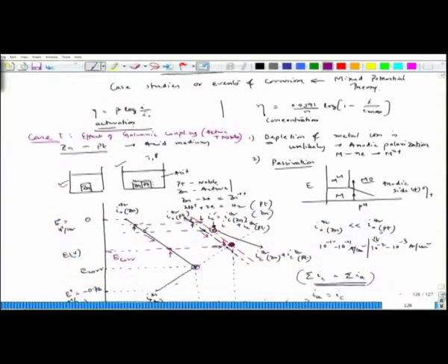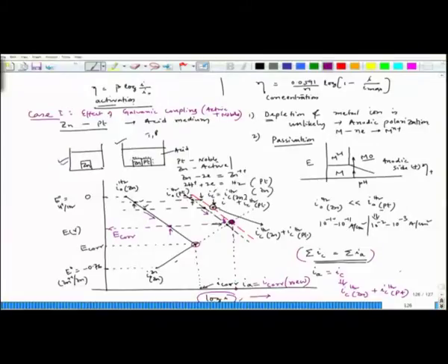But remember, when we have seen this galvanic coupling, we have said that they have the same area exposed to the acid medium. The area is not changing. The active component has some area, let us say 1 centimeter square, then platinum would also have the same area. Now, interestingly, if it is connected to another component, let us say instead of platinum we add platinized platinum, in that case the corrosion rate would further increase.